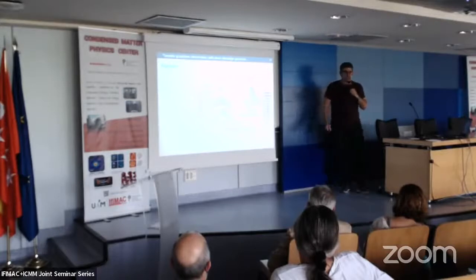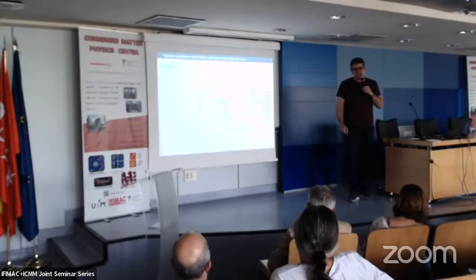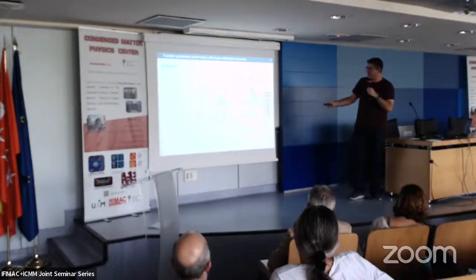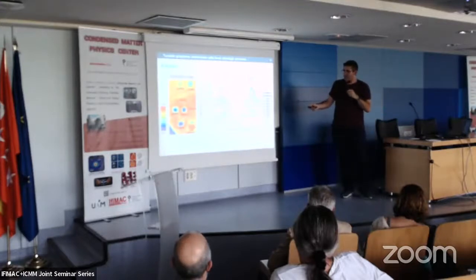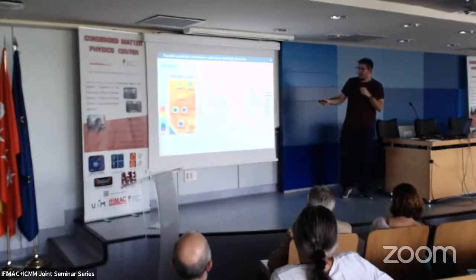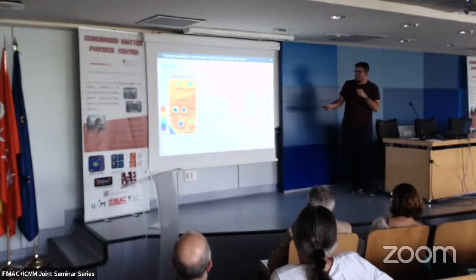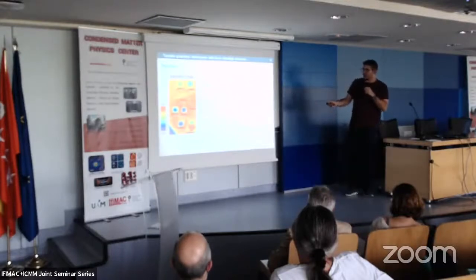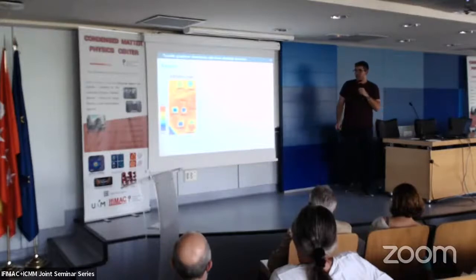But if you check the literature, the main magnitude that tells us about doping is the intensity relation between these two peaks. So we can map that, and if we get a map of this intensity relation, we can see how, for example, for 16 gigapascals there is no change, but when you increase 20, 25, 32, 34, 37, there is a constant increase in this change. So if we plot this intensity relation as a function of the pressure, we can see again that we can precisely control this magnitude with the pressure, and this magnitude is related to the doping.